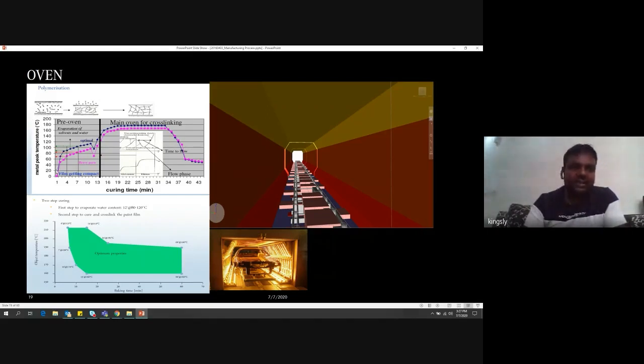So for this, we have to heat up this paint first for 10 minutes at 110 degrees Celsius. Then we have to heat it again from 110 to 180 degrees Celsius. At 180 degrees Celsius, we have to keep it for 28 minutes in the heat oven. Then we have to cool down to normal temperature, below 40. So when we do this kind of process, the paint gets polymerized. Polymerized means the cross-linking is formed in the paint, you can see here. And this will give good adhesion to the metal or steel and the paint material.